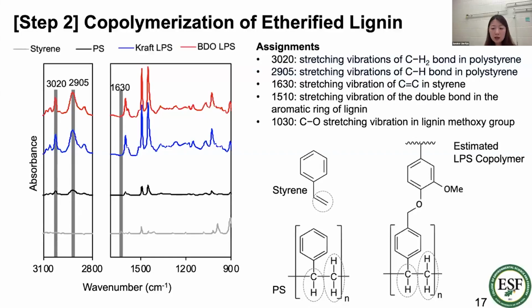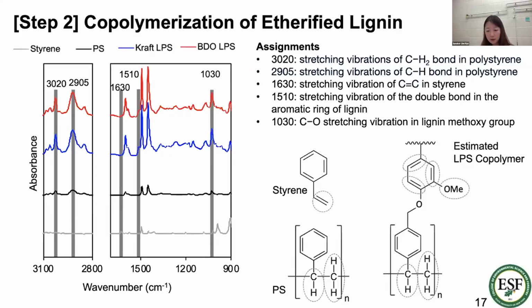Then how can we see that the lignin is introduced into the polymer system? There are two assignments: the C-O bond in the methoxyl group, and the C-C bond in the aromatic ring structure. The aromatic ring structure showed up as a shorter peak at 1500 wave number, and the C-O stretching vibration derived from the methoxyl group showed up at the 1000 wave number area. So we can say that the modified lignin was successfully copolymerized in the LPS polymer system.